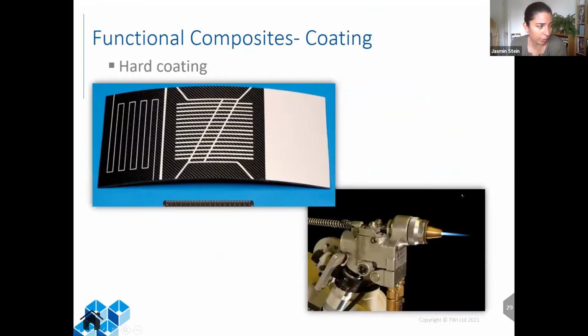And then the hard coating, this is an example of thermally sprayed composite. And what you can see here is the carbon fiber composite with aluminum coating. You can either fully coat the surface, or you can put different patterns. We have the automated system for it. But special is the way TWI has developed the method in order to spray this without damaging the fibers. That's the main expertise of TWI.